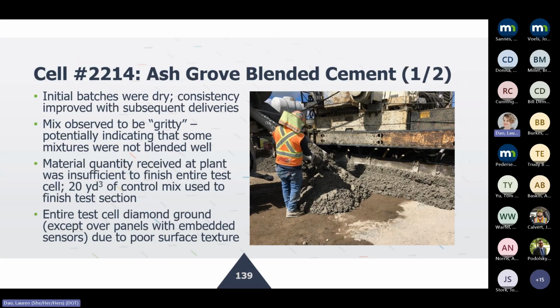All right, the next material was the Ash Grove blended cement, and similar to the ultra high materials, the initial batches were relatively dry, but with subsequent deliveries it did improve. But one issue we had, not just on this project but on the carbon dioxide and the alternative pozzolanic projects, was the delay in getting the subsequent mixes, up to 45 minutes to 1 hour of wait time in getting the trucks from the batch plant to the site. That was also a big issue with a lot of these mixtures. And we did notice that this mixture was not blended very well.